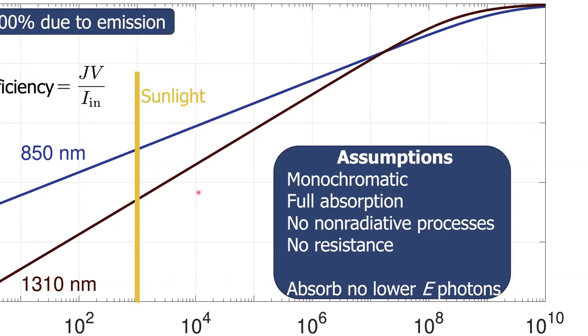So just to give a sense of scale here, not talking about QED processes, sunlight, though it is not monochromatic, is about, under full sunlight, about 1,000 watts per square meter. Now, the highest efficiency monochromatic conversion device was made by Simon Fafard, who is known to many of us, in collaboration with Karen Hinzer's group here at the University of Ottawa. That was a 70% device operating close to 850 nanometers and at this power density.